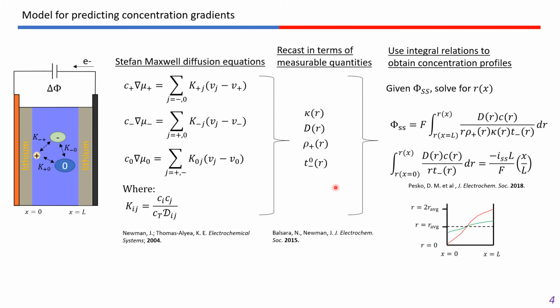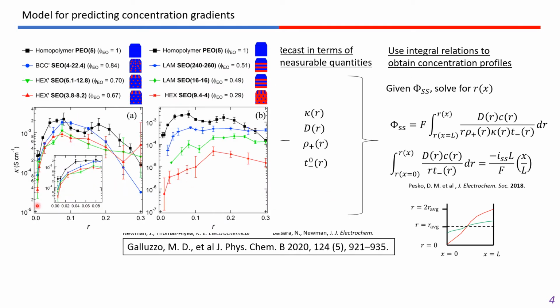And while I don't want to belabor these points or these measurements, I just want to say that we've measured these parameters. Here I'm showing the conductivity as a function of salt concentration for a variety of different block copolymer SEO electrolytes with different morphologies and chain lengths.